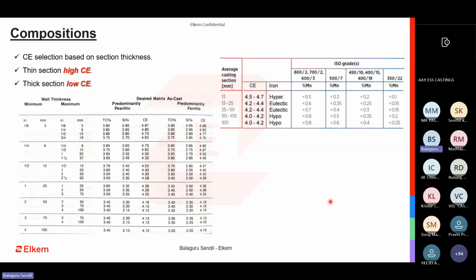So again, we have multiple grades of cast iron. When you are going to look into selection of carbon and carbon equivalent, you have to ideally refer to the section thickness you have, what the minimum and maximum are, and select the correct carbon value for your casting. Do not go for high just to solve the problem of shrinkage, or keep it too low, because then you are getting very low mechanical properties. That is also not an ideal situation.